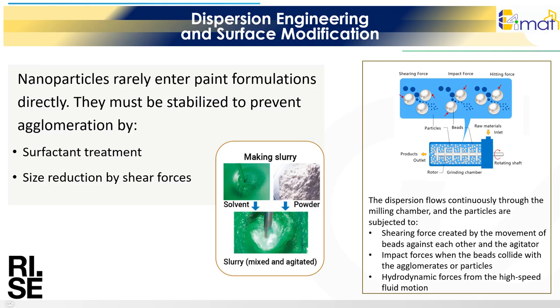Together, these forces break down particle clusters, reduce particle size, and produce a uniform and stable dispersion. Importantly, bead milling makes it possible to reach high nanoparticle concentrations, up to 38%, while maintaining consistent particle size and dispersion quality. This capability offers a major advantage for applications that demand highly loaded formulations.